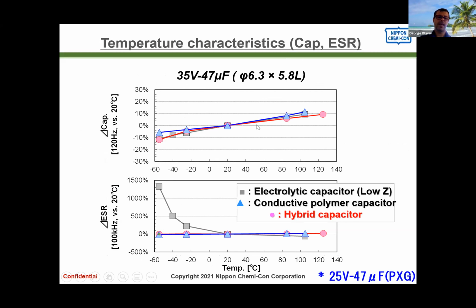Temperature characteristics, again, if you look at the electrolytic capacitor and then you look at the hybrid capacitor, especially on the ESR, if you look on the bottom side, you see that once the temperature decreases below, especially below 0, you'll see the ESR of the electrolytic capacitor really skyrocket. It goes up significantly versus a polymer or hybrid, which essentially stay the same.